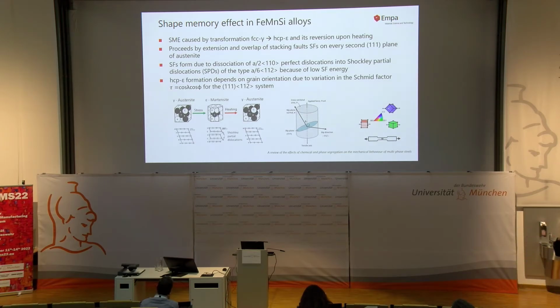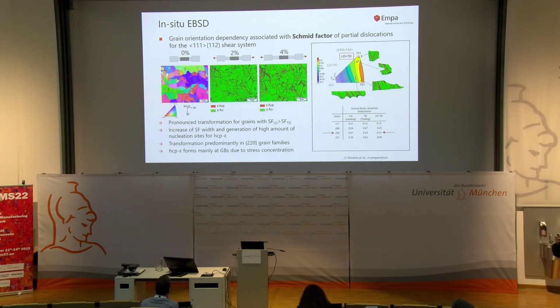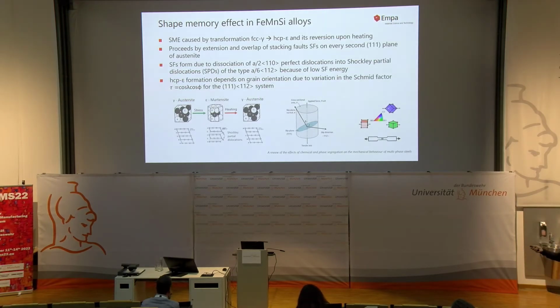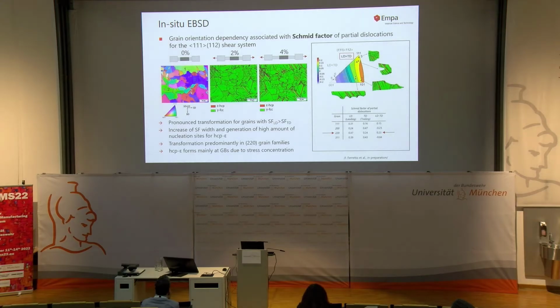And we try to understand now what the criterion is, so which grains are really active and which grains are not. And so we started to calculate the Schmid factors. So Schmid factors, that's exactly this. Tau is, so here we have the cosine of this angle, slip direction, angle slip plane normal. You can look that up in textbooks and start calculating for that, but we did that for the partial dislocations.